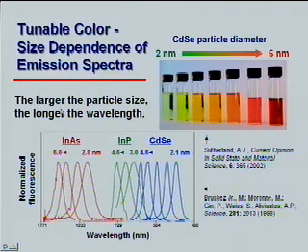As you can see, the larger the particle size, the longer the wavelength. We can also easily adjust the size of the particle in preparation. So that means you can adjust the color easily by changing the size of the particle.